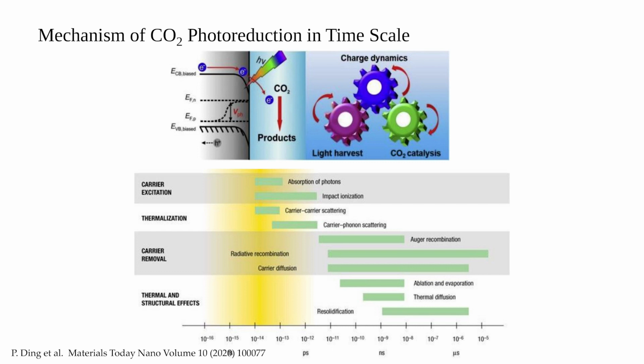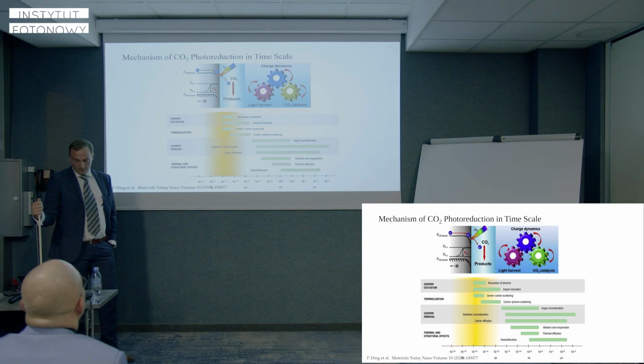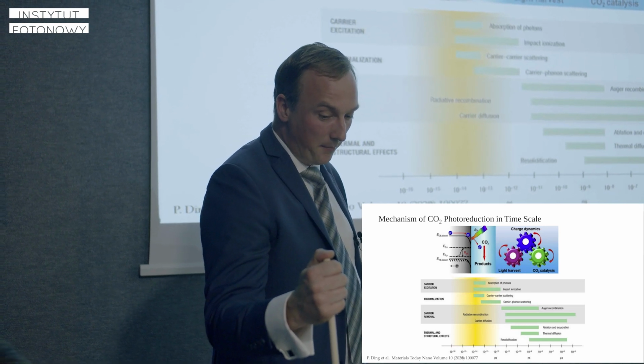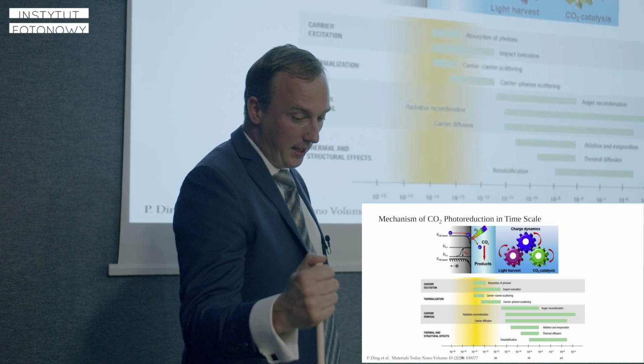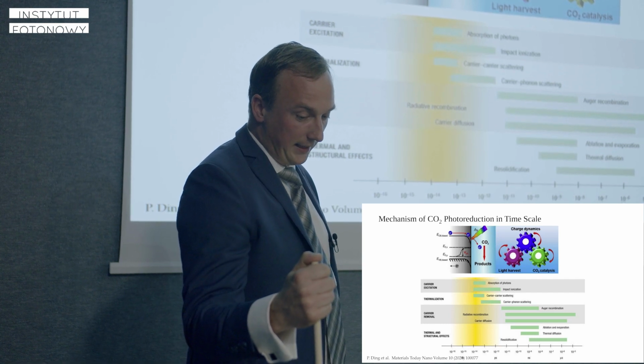Challenges of photoelectrochemical carbon dioxide reduction generally lie in 3 aspects: poor light absorption, inefficient charge separation, and slow surface catalytic conversion. The light absorption range is largely determined by the band gap of semiconductor materials, also by their surface properties. Even if the light absorption is good, photoexcited charge carriers sometimes are subjected to serious recombination as mediated by surface states, defects, or impurities. The transport of minority carriers towards the surface is largely dependent on the electronic structure of the interface and may become impeded when the built-in electric field is weak.